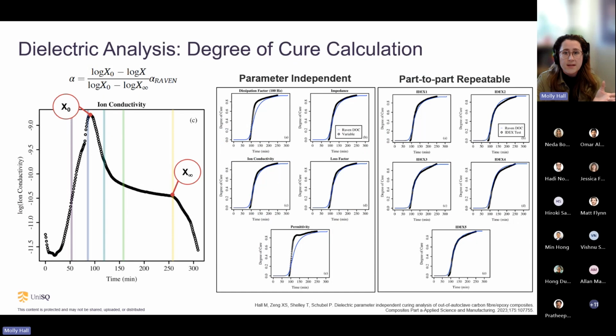So aside from our cure points that we can identify, there are several ways of calculating degree of cure out of these signals as well. So this is an equation that has been proposed for some of the parameters previously. And again, we've shown that it is also parameter independent, and it can be applied to any of these signals with decent success. So what we do here is we sort of cap the beginning of the equation we're considering at that global maximum, where the ion movement is the dominating contributor to your cure reaction, and then we cap it at the end of the cure reaction. So when we're stopping that reaction rate.